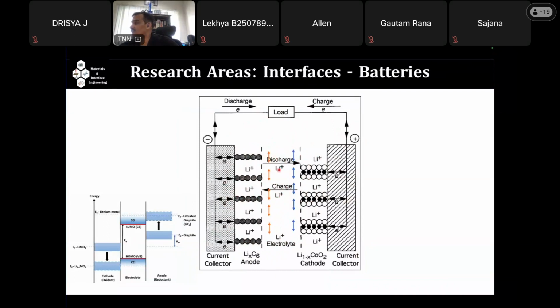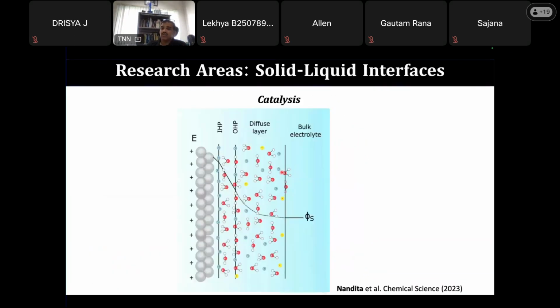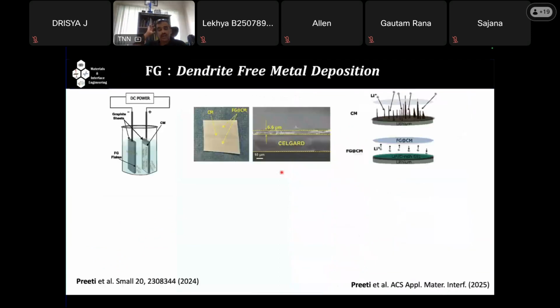We cannot externally make the solid electrolyte interface, because if you do it externally, then the thickness matters. If you have a very thick solid electrolyte interface, then the ion transfer itself will become a problem. And as I told you, it has a mixture of components. So putting an actual component at the interface which will be conducive for lithium ion transport will be very difficult to identify, because depending upon the system, the electrolyte, and the electrode, the components of the interface can be different.